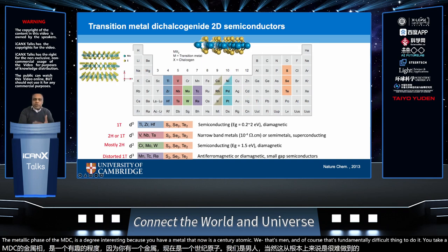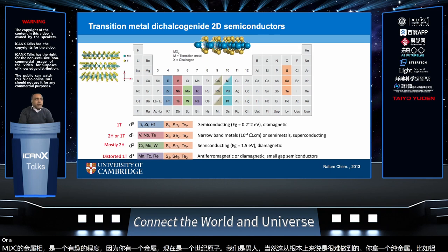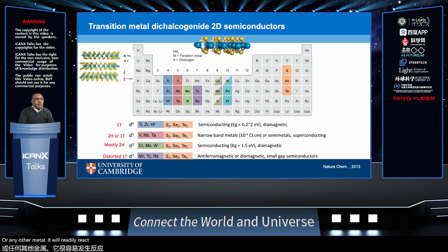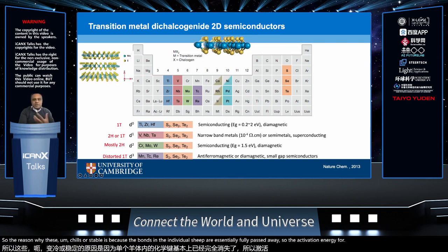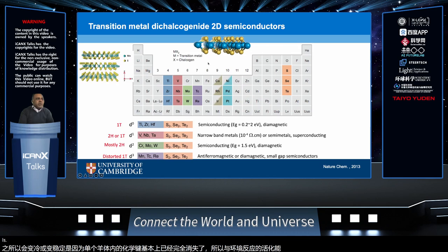If you take a pure metal like aluminum or any other metal, it will readily react with the environment and be inherently unstable. So to be able to isolate these atomically thin sheets and for them to be metals is quite significant because it opens up lots of different interesting applications, especially in electrochemistry. The reason why these materials are stable is because the bonds in the individual sheet are essentially fully passivated, so the activation energy for reaction with the environment is quite high.